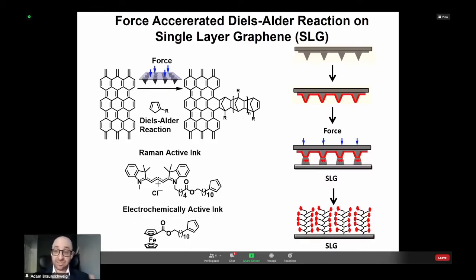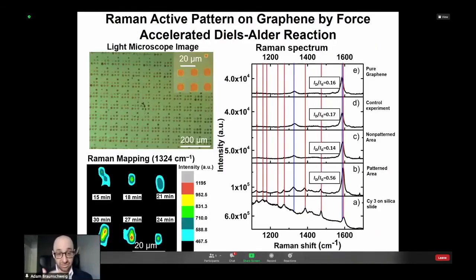So it's hard to do fluorescence on graphene. So rather than create a fluorescent ink, we created a Raman active ink as well as an electrochemically active ink. And both of these have a diene, cyclopentadiene, that we attach to the ink. Then we would put this ink on our tip, apply a force, and hope for patterning. So this is what the data look like. What you see is we can pattern small features about 5 microns over large centimeter scale areas.